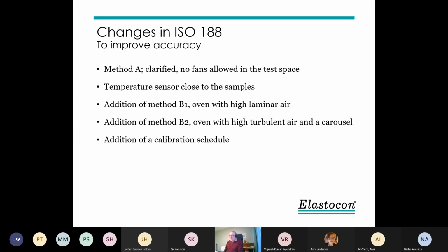This work we made many years ago later led to improvements in the ISO standard. We've done that a couple of times. We have the method A, which specifies a low air speed, was clarified. There are not allowed any fans in the test space to keep the air speed very low. Also to have a temperature sensor close to the samples.